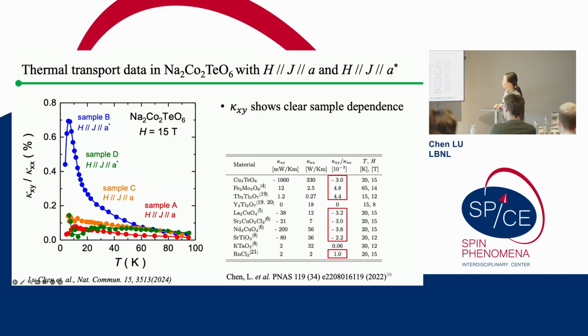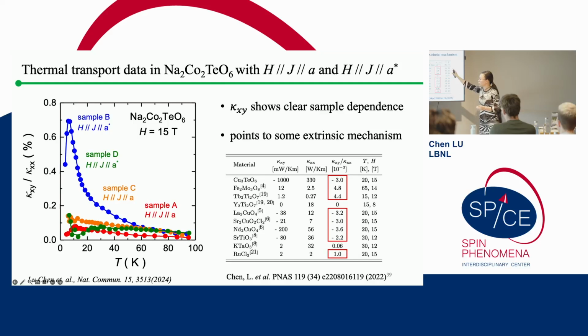One thing here is that this strong sample dependence probably indicates that the mechanism is some kind of extrinsic mechanism, because it could be linked to the sample quality of this material, like impurities, defects, dislocations, and everything. This induces the sample dependence. However, even though the thermal Hall angle shows a big difference between samples, they are still very comparable to other systems where a phonon thermal Hall effect was measured, which means the thermal Hall angle lies within about 0.1% to 1%. This is the other evidence that we usually ascribe this signal to a phonon thermal Hall effect: the thermal Hall angle lies within this range.